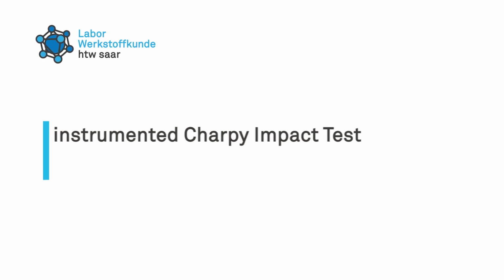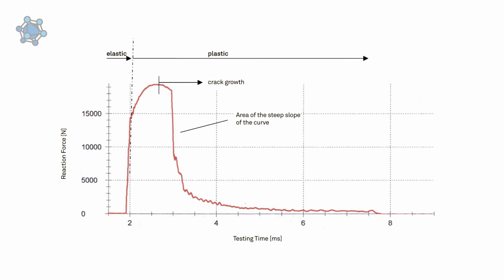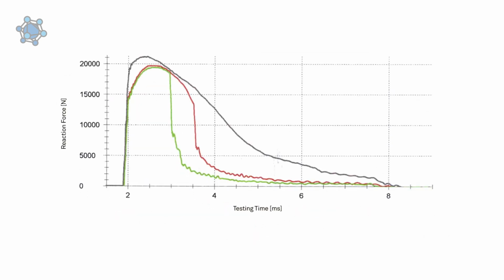Finally, let's move on to the instrumented Charpy Impact Test. In this variation of the test, we not only measure the V-notch impact energy, but also the force curve over time via a force transducer in the striking edge. Analyzing this curve can also help us determine the fracture behavior. If we have a very steep force drop after the force maximum, that's a specimen with low Charpy impact work exhibiting a brittle fracture. If we have a slow drop in force at first and then a steep drop, we can determine a mixed fracture.